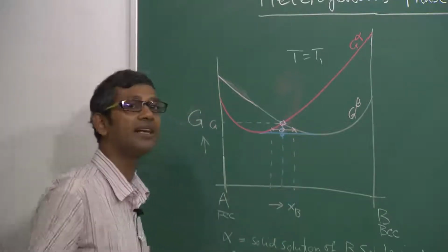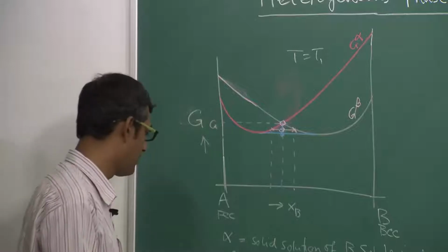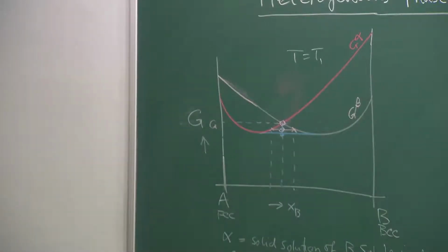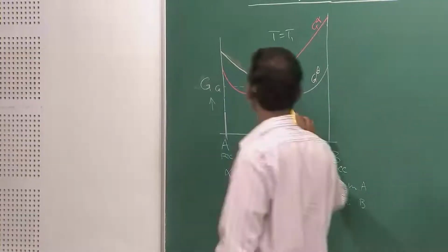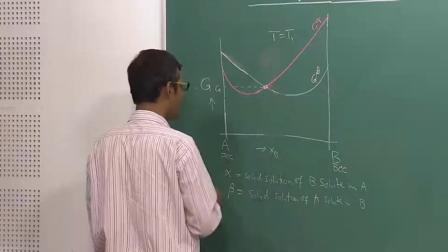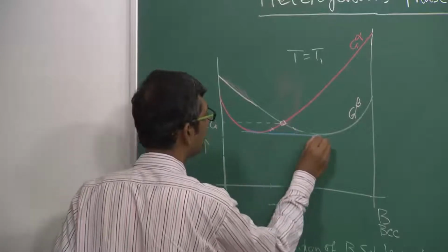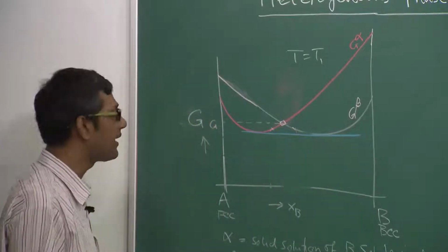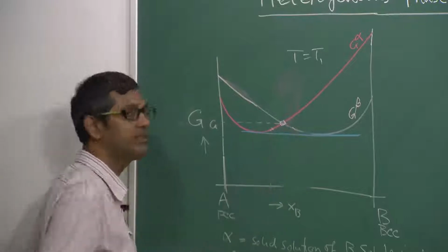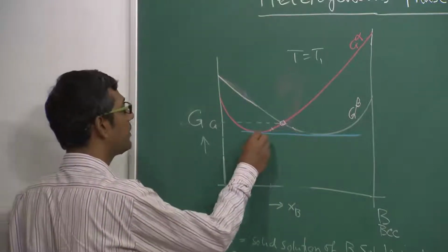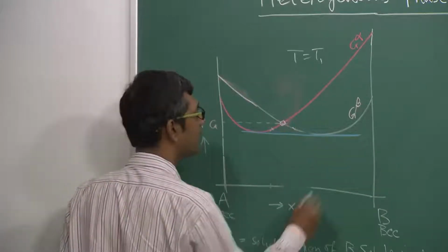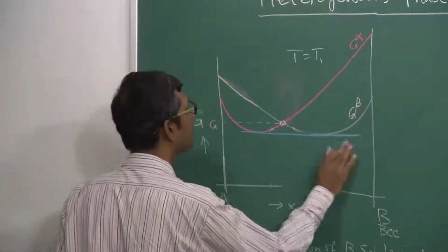So now the question is how far we can go down. That will be clear to you once I erase that part a little bit and explain to you. It is very clear that if I erase these things and draw a nice plot, then if I draw a common tangent between these two, I will be touching the lowest portions of these free energy curves, and therefore it cannot reduce any further below, because I cannot draw a straight line like this, it is not going to be mathematically correct.